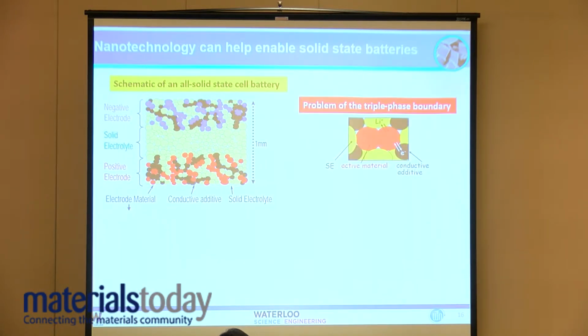So the problem is really one of what we call a triple phase boundary, which is that in a battery, the electrons have to find their way to the active cathode material to do that redox chemistry at the same time as the ions that move from the solid electrolyte enter that material. So at these junctions of the electrolyte and active material, we have this triple phase boundary, and the more triple phase boundaries you have and the more intimate that contact is, the better the cell will work. So clearly trying to make solid-state batteries work on 5 micron or 10 micron particles is going to be a real challenge.